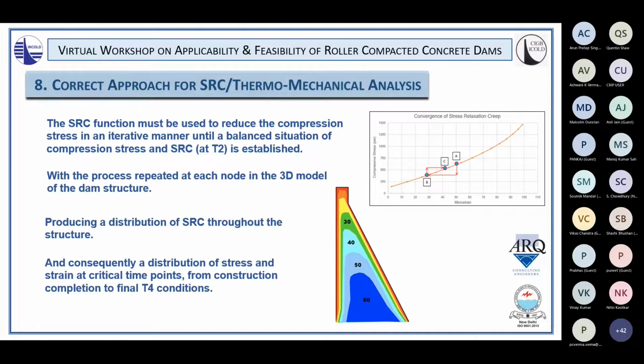And very typically, we'll see a picture where we have higher levels of stress relaxation creep in the lower parts of the dam structure, reducing with height, again not simply related to the dimensions or the temperature rise of the structure, but significantly related to the level of flexibility of the structure higher up. And this gives us then a situation, we have a distribution of stress and strain at the critical point in time, and from that condition, we can then derive what are the stresses and strains in the structure at any subsequent point forward until full dissipation of the hydration heat at the T4 conditions.